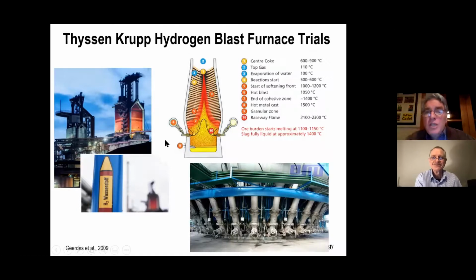So the blast furnace has all these tuyeres where you inject your gases, and this is where they're injecting the hydrogen. And what they're finding is that as you inject the hydrogen, you create energy balance problems here, because the reactions between hydrogen and iron oxide are endothermic as compared to exothermic with carbon. Reminding you of high school chemistry: endothermic sucking in the heat and exothermic pushing out the heat. So these endothermic reactions cause all sorts of issues down below here, in this area, what they call the raceway in blast furnace parlance.